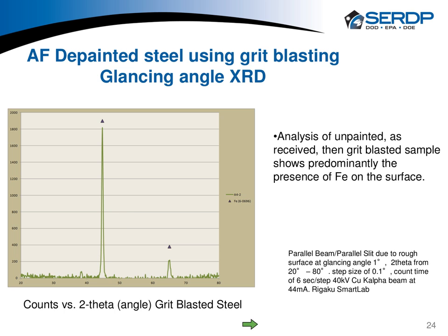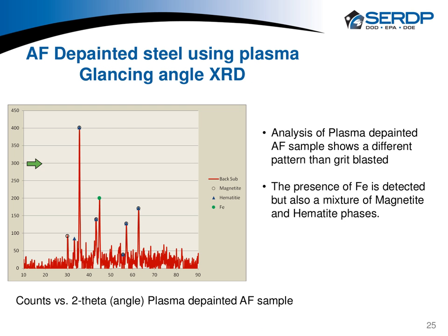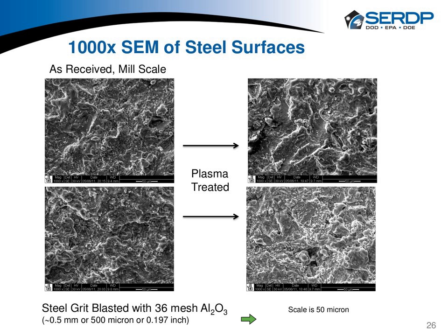Well, this was interesting compared to the grit blasted sample. First of all, the counts are much less, so there's a lot more noise here. But the primary species that we found here were oxides of iron with traces of iron deeper into the surface. So this gave us further evidence that the plasma was creating an oxide on the surface, and that makes sense. Now, from our point of view, that was good news because we felt that these oxides were very stable and controllable, and without metallic iron there, the potential for this surface to rust in the future would be minimized. So we deemed this as a good result in terms of a protective coating that was formed on the surface.